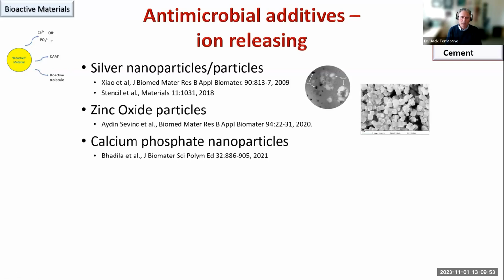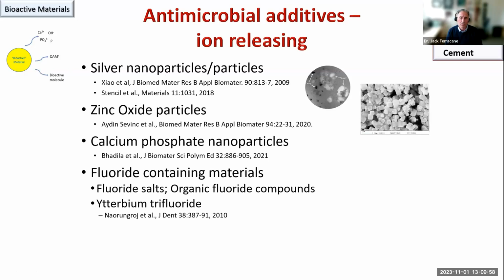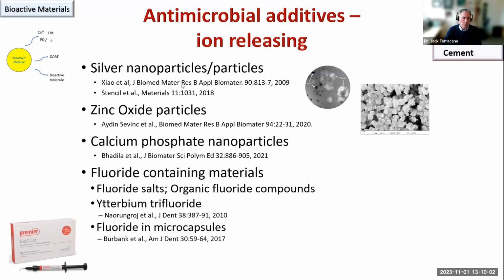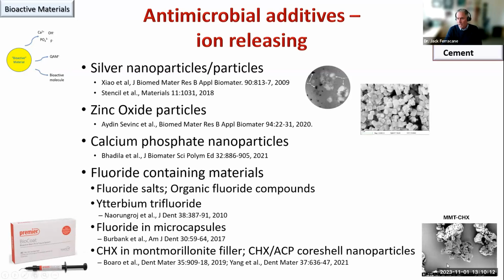We have calcium phosphate nanoparticles, as calcium has an antibacterial effect itself. We have fluoride-containing materials, and we've seen fluoride produced and put into microcapsules in a material like BioCoat from Premier, where it will have a slow release over time to give a constant environment of fluoride. And then some interesting work in trying to add something like chlorhexidine into a porous filler that could be added into a composite and would release this antibacterial compound over time.